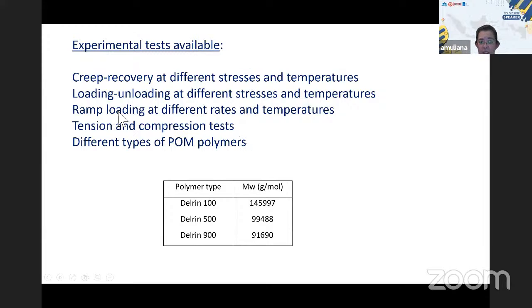history of testing. So this is like creep recovery at different stresses and temperatures. By creep, we mean we load the specimen up to a certain load and keep it at a constant load. Then we would see the deformation, or the strain, continuously increase with time. This is what we call creep loading. And we also do loading, unloading. We would be able to see a hysteretic response. And we also ramp it until failure.